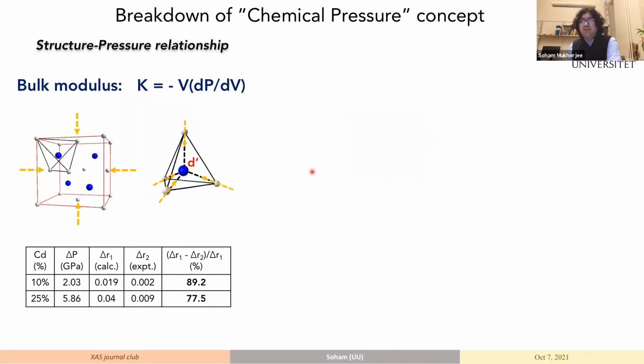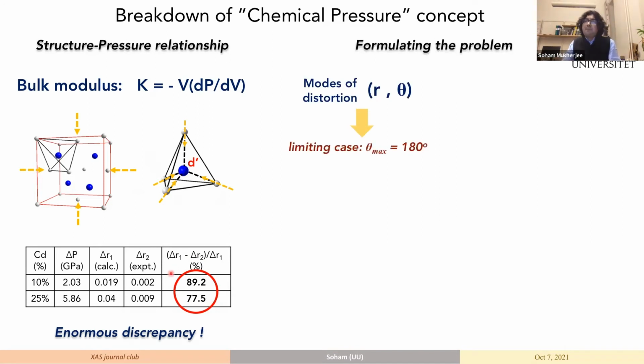And where it fails is that when we do the pressure-structure equivalence by following the bulk modulus, for example, we see that for the 10% and 25% samples, this is cadmium doping, when we plug this into the equation, there is an enormous amount of discrepancy from what the chemical pressure would predict. So this sample clearly doesn't follow the chemical pressure predictions, as what we observe from the distances. Now, we wanted to tackle this problem, and to do that, we thought of a system where we'd formulate the problem in such a way that we can see the effect of the distance and the angle separately.